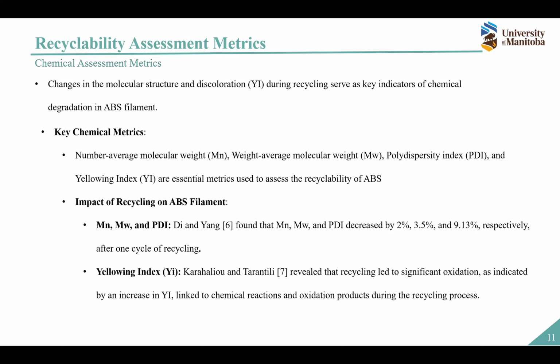The last assessment metrics is chemical assessment metrics. As you can see, the molecular structure and also discolorations serve as key indicators of chemical degradation. So how can we measure this type of degradation? By measuring number average molecular weight, weight average molecular weight, polydispersity index, and the yellowing index. These are the most important metrics that we can use to assess the recyclability of ABS.